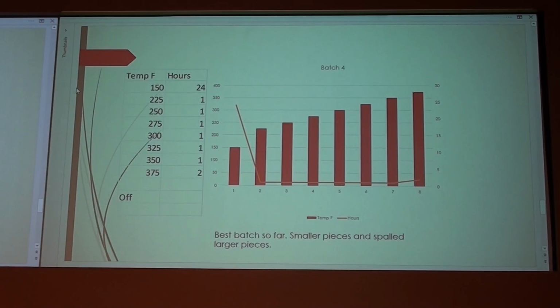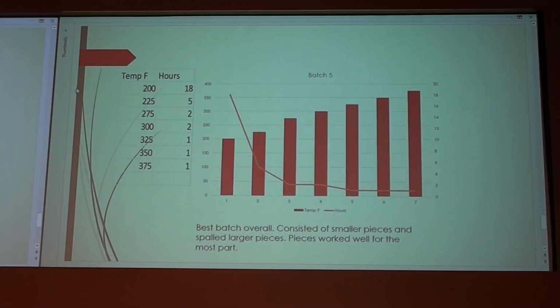And so this one here, I did spall the larger pieces. It was the best batch so far. The pieces worked pretty good. This one here, smaller pieces, spalled, larger pieces. Same thing, 200, did a good soak on it at a lower temperature to drive the water off, and then went up to 375 and turned it off, and it turned out to be a good batch.